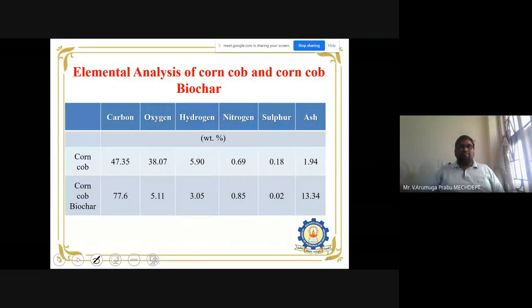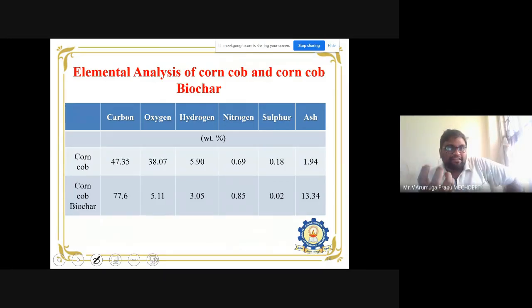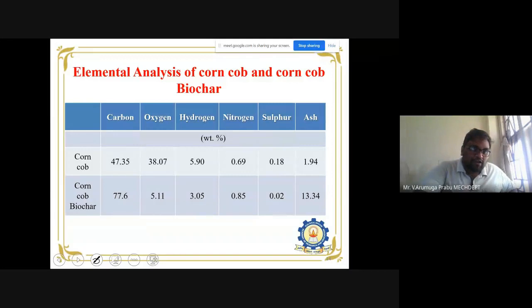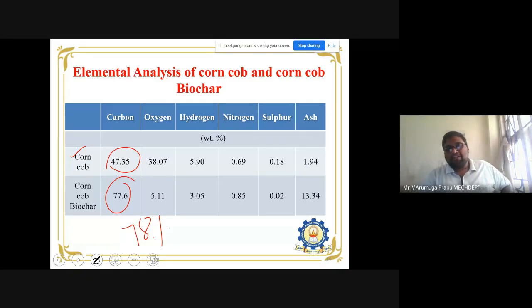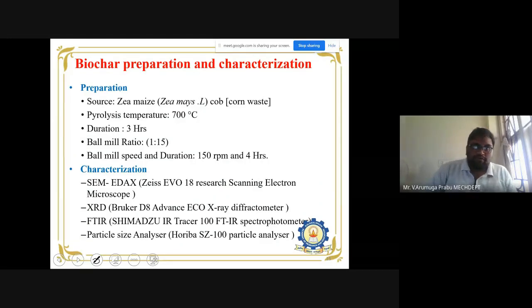This is the elemental analysis, and the interesting thing is the composition present in your biochar. This is your ordinary waste corn cob, which has a carbon percentage of 47, whereas the biochar obtained from these corn cobs by means of the pyrolysis process has a very high carbon content of nearly 78 percent. That will make this corn cob biochar an effective reinforcement for making advanced composites. Because as we all know, carbon is one of the highest strength materials. If the carbon content is there, it surely produces the highest strength. So this is how we are producing the biochar.